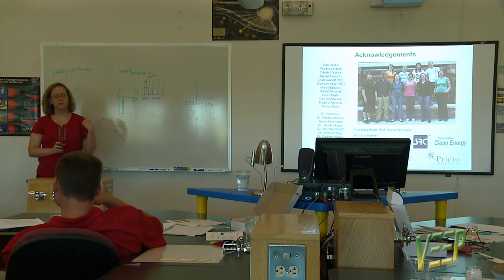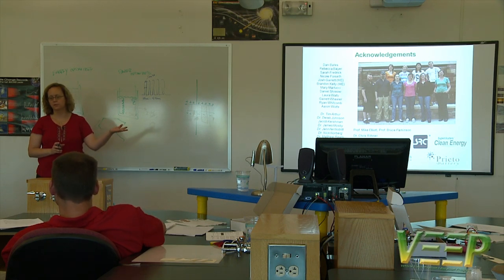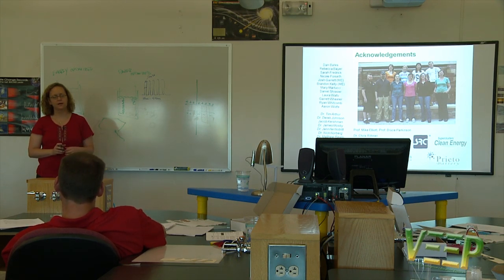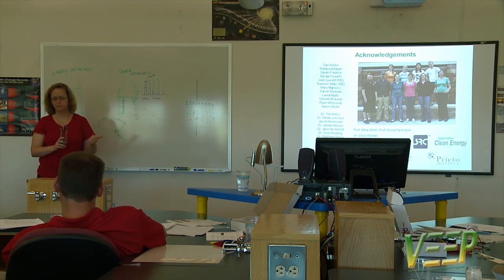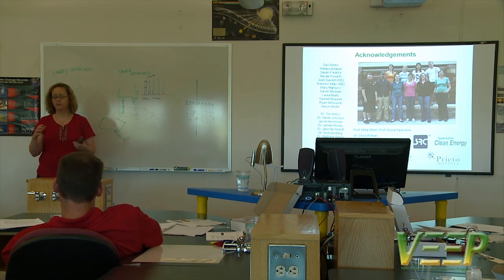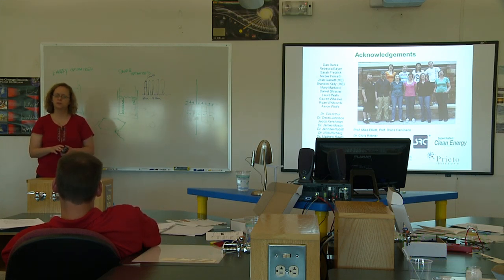So when we were trying to design our polymers, we decided it was faster to use this copper foam as a tool. But then when we calculated what the performance of that foam should be, we realized that that probably was a good first battery. It's also cheaper. When we do the manufacturing cost calculations, these extra steps add quite a bit. So instead of 348, the nanowire battery is about 570. So it's a lot more expensive. The power density is way higher, three orders of magnitude higher. But it's just trickier to make.